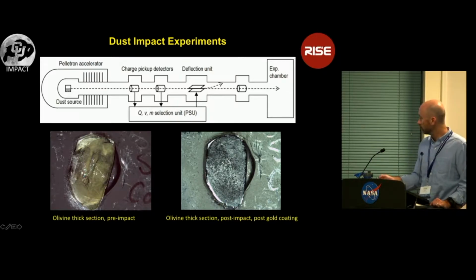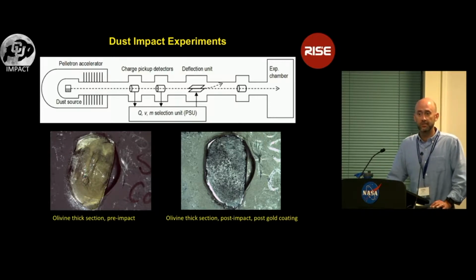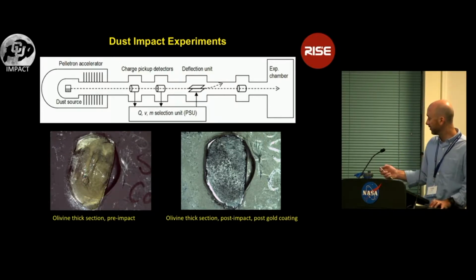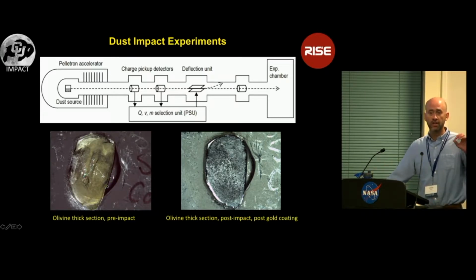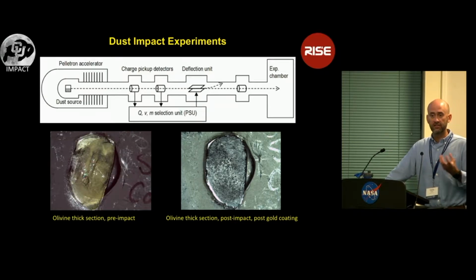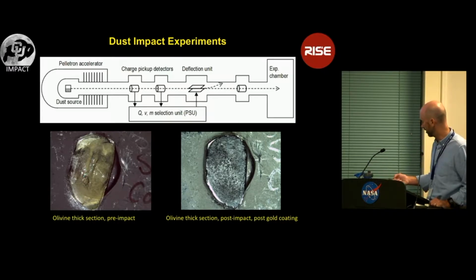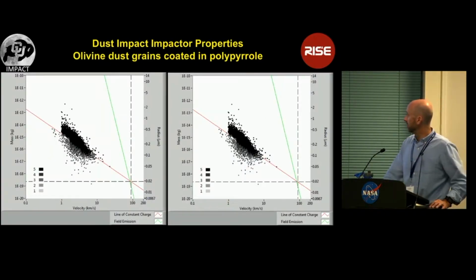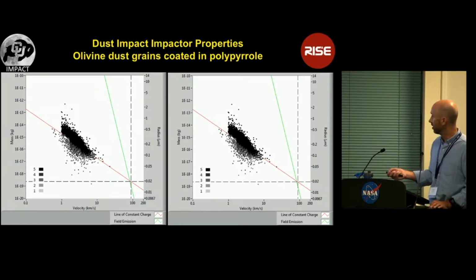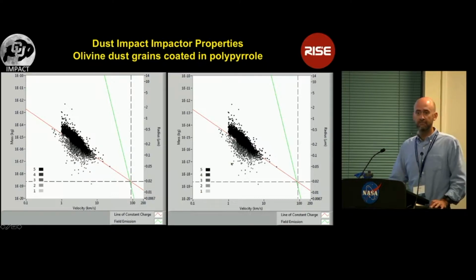the impact as well. So for these impact experiments, our dust particles that we were using were made of olivine, so roughly the same material as our target. Those olivine particles were coated in a conductive organic polymer called polypyrrole, but it allows us to avoid using metallic projectiles, which some other investigators have done. Here are the statistics for our 2 samples. Here is our sample that has been irradiated before the impact experiments, and here's a sample that has not been irradiated but impacted. Each sample was impacted roughly 10,000 times over a course of about a day.